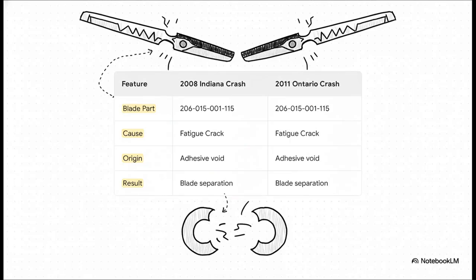I mean, when you put the findings from these 2 crashes side by side, it is just uncanny. It's the same blade part number, the same failure cause, a fatigue crack, and the same origin point, a void in the adhesive inside the spar. It was the exact same hidden flaw causing the exact same catastrophic failure.